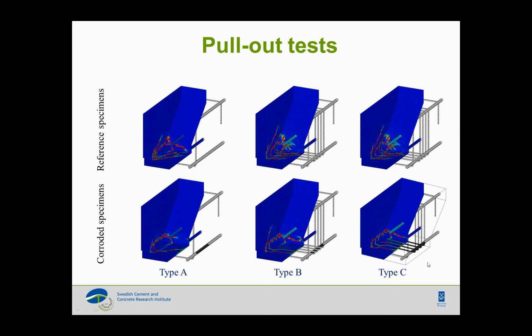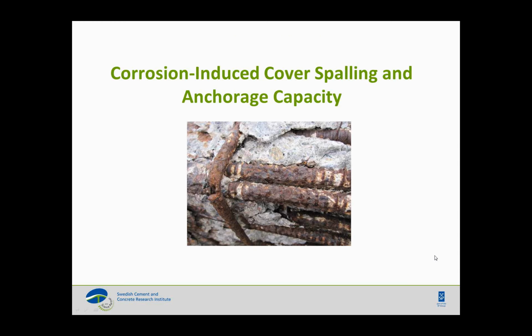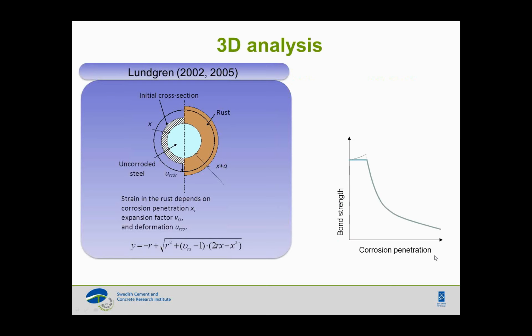Then the third aspect that we wanted to implement in our simulations was: what happens if we go far into corrosion and then we get into cover spalling, because in simulations we always have a problem as soon as we get to high crack width. So starting from the original model, we just take into account the swelling effect of corrosion product. If we look at this schematic illustration of the relation between bond strength and corrosion penetration, as we saw earlier, we start with this part in the beginning where we have a little bit higher bond capacity. We do not take that into account in our simulation, but as soon as we get to cracking, then we have a sharp drop in the bond strength.